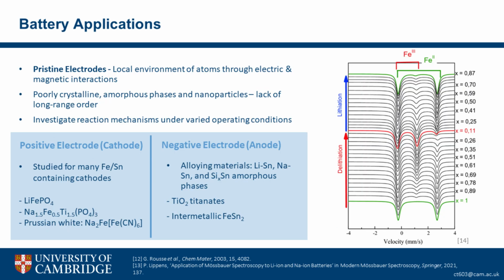Right, so just in general, battery applications of Mossbauer spectroscopy, it's really useful for studying pristine electrodes. It's quite a good local probe of the environment that atoms sit in the crystal structure, and it can give you a lot of information about the electric and magnetic interactions of the ions. It's also really good for studying poorly crystalline, amorphous, or nanoparticles, where you would typically struggle to use X-ray diffraction to characterize the materials. And it can be adapted to a lot of operating conditions because it's such a simple setup. And so you can investigate a lot of reaction mechanisms under Operando conditions.